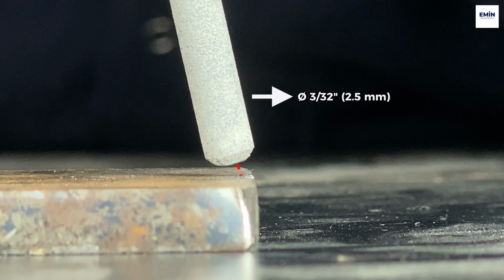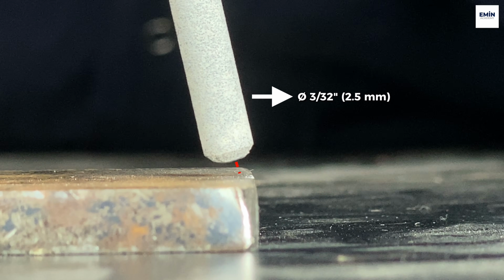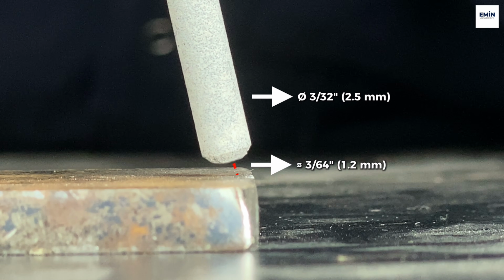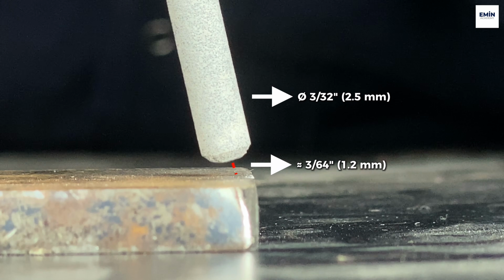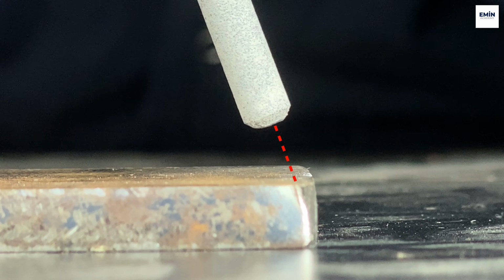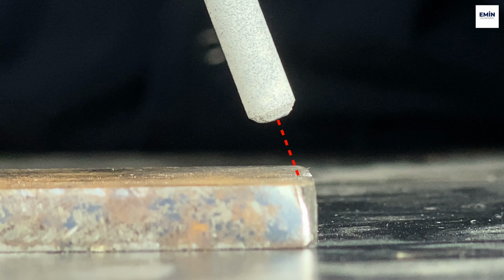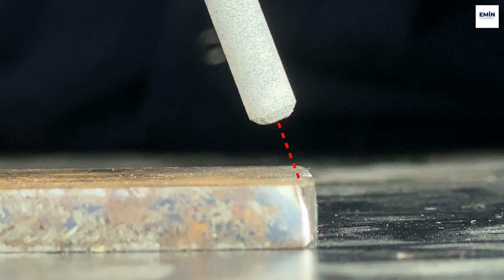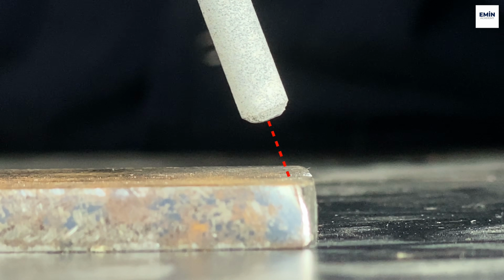After the arc starts, the arc length should be kept at about half the electrode diameter. For example, when working with a 3/32 inch diameter electrode, the arc length should be kept around 3/64 of an inch. If the arc length is too long, the arc becomes unstable and spatter increases because the distance between the electrode and the part increases. At the same time, the shielding effect created by the electrode coating also weakens. This can cause the molten weld pool to come into contact with air and create porosity.